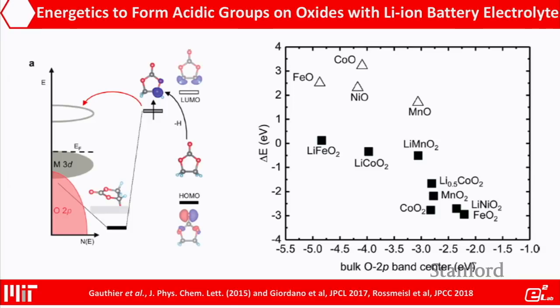So the more you charge the battery, the metal oxide becomes more covalent, and we find there's increasing driving force for the metal oxide surface, essentially to dehydrogenate the solvent. Essentially to take a hydrogen from the solvent and create a protic species on the metal oxide surface. And the driving force you can see is up to 3 eV or 300 kilojoules per mole. It's a very high driving force.